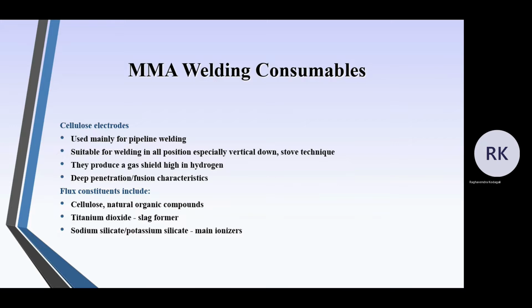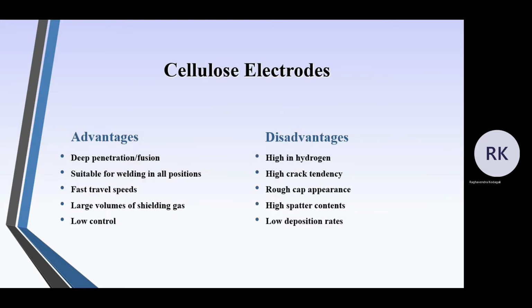Manual welding consumables, cellulosic electrodes are used mainly in pipe welding, suitable for welding in all positions, especially vertical down and stovepipe technique. They also produce gas shielding and are very high in hydrogen. So deep penetration fusion. Flux constituents include cellulosic natural organic compounds. Titanium dioxide is a slag former, and sodium silicate and potassium silicates are the main ionizers.